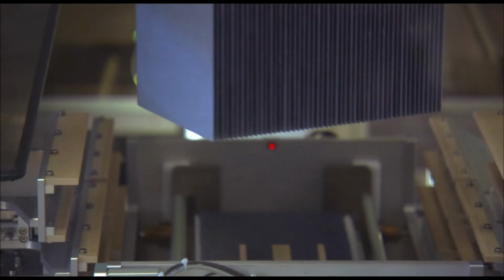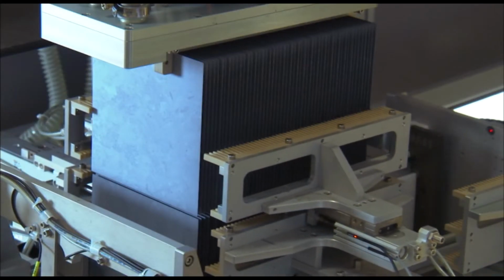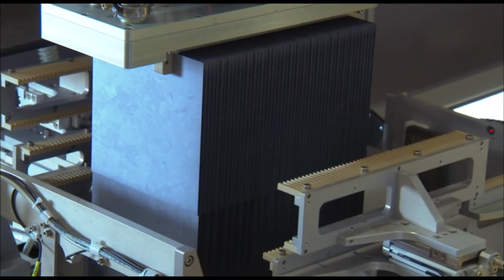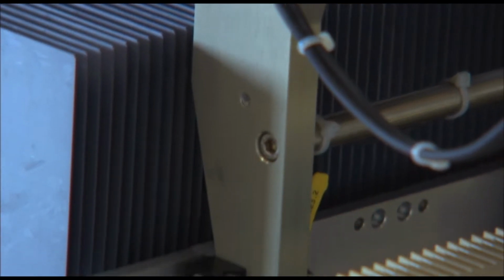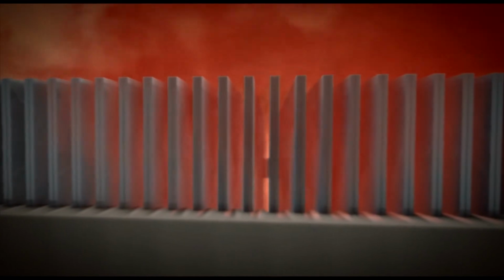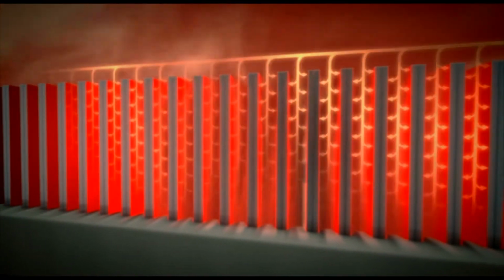Before this point is reached, however, our wafers must pass through a number of processing steps, the most important of which is probably a phosphorus diffusion step. In pairs of cells, placed back-to-back with one another, the wafers enter a tube furnace, where they are heated to over 800 degrees Celsius and diffused with phosphorus gas. This gas condenses on the open surfaces of the wafers. It penetrates the wafer and forms two layers with differing electronic characteristics based on their respective atomic structures.